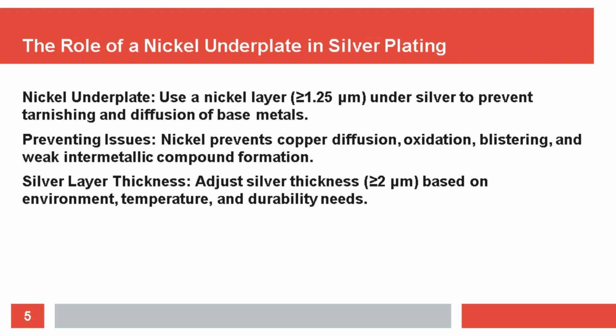Additionally, without a nickel layer, oxygen can diffuse through the silver to the copper base, potentially causing blistering. Nickel also prevents the formation of weak silver-copper intermetallic compounds at temperatures above 150 degrees Celsius. These compounds can create adhesion problems, making the silver layer less durable and effective.